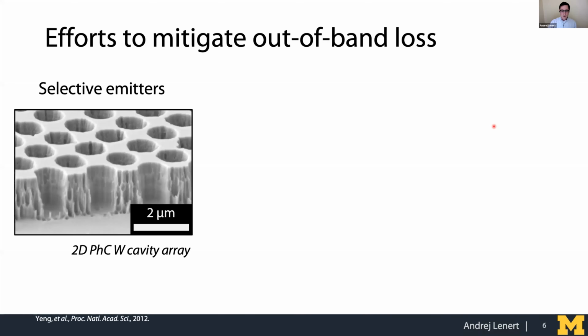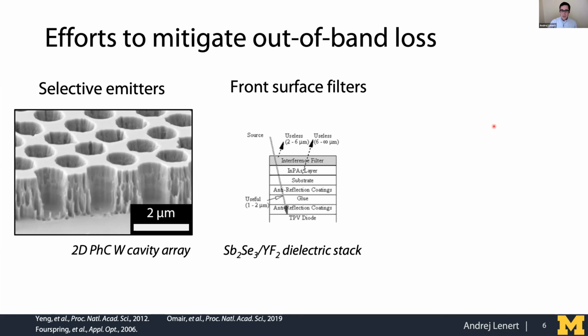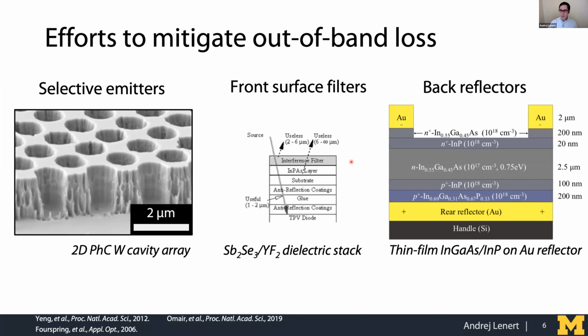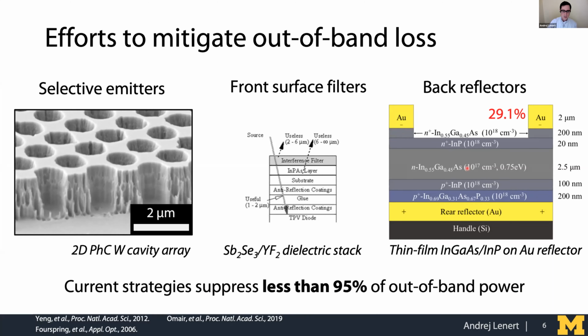And in terms of the efforts to accomplish this mitigation of out-of-band loss, which is so critical to efficiency, there's been work out of MIT to develop selective emitters. There's also been some more older work looking at front surface filters. So these are filters that are put on top of the cell, and that through interference and plasma achieve reflection across a broad band. And really the devices that have achieved the highest efficiencies rely on back surface reflectors. So these are really good mirrors that are placed behind the absorber. And this architecture is the one that was used by the Berkeley group to achieve 29.1% efficiency.